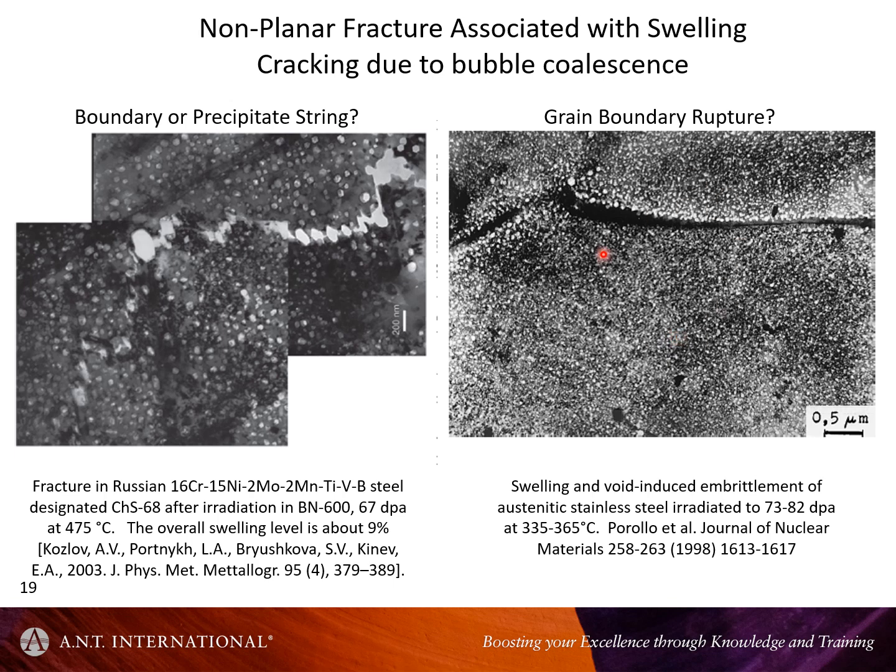This is in very high density cavity situations. But this is generally not a planar thing. In this particular case, this is Porollo. The cracking is actually along the boundary, and there seems to be a higher density of cavities along some interface here. Hard to say. I would have said that's intergranular probably.